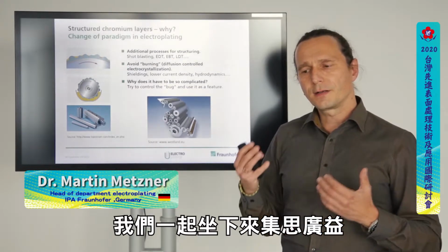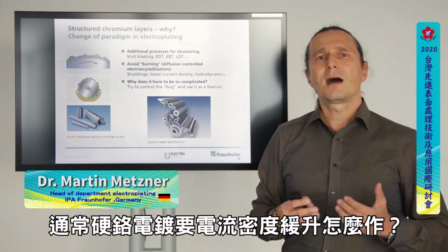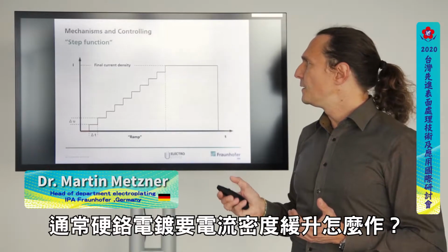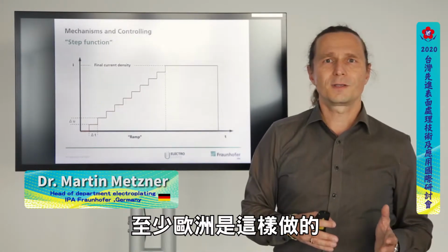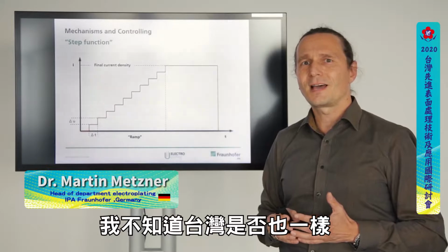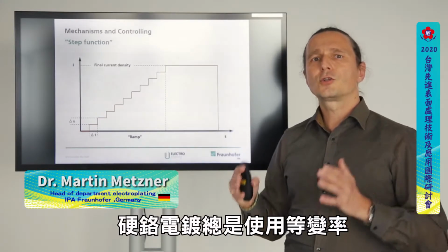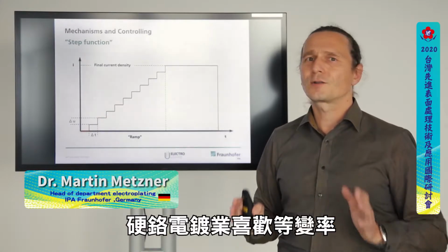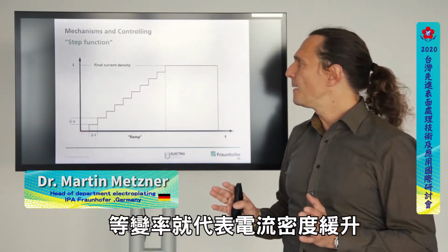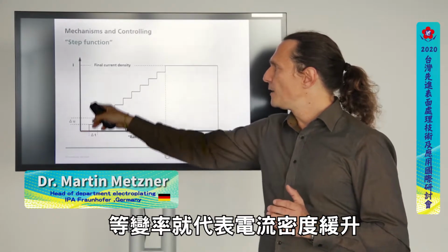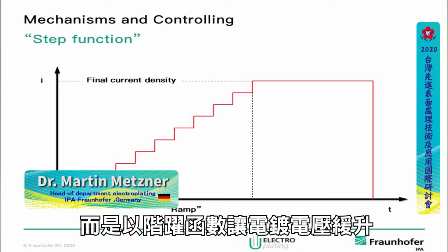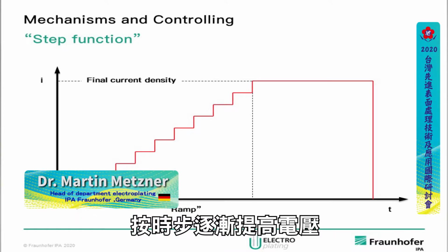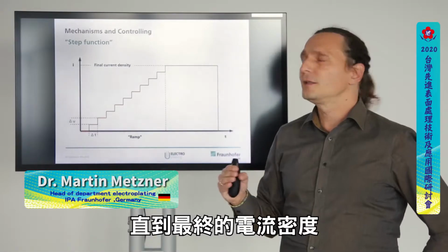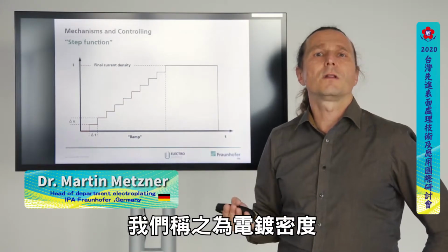And then we sat together and thought about what the normal hard chromium plater does when he ramps up his current density. At least in Europe he does this. I do not know if it's the same in Taiwan, but I think so. The hard chromium plater always uses ramps. Hard chromium platers love ramps. Ramps in fact means they ramp up the current density. Of course, they ramp up the plating voltage in a kind of step function, step by step up the voltage in different time steps until they reach the final current density, what we call the plating density.